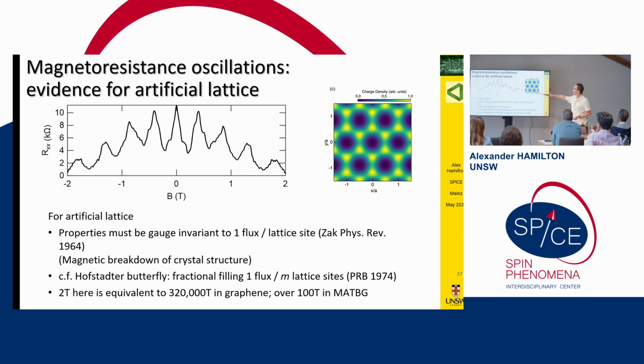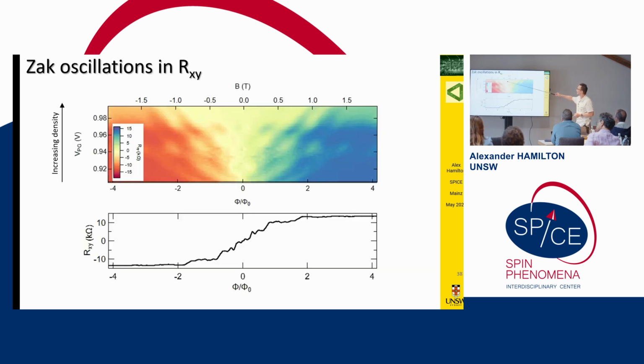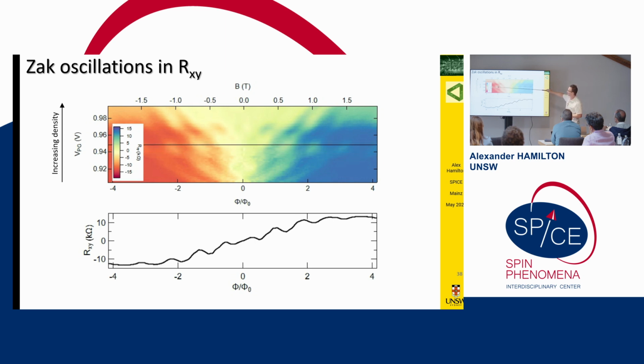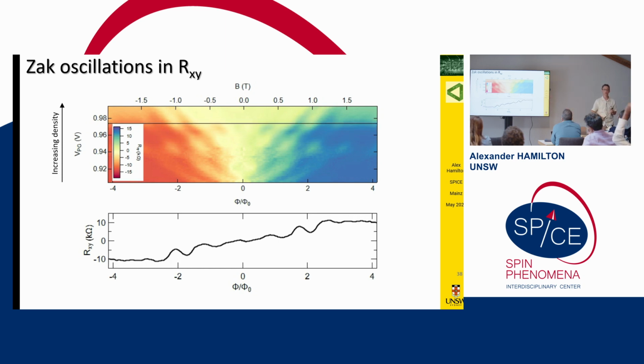So for us, going from 0 magnetic field to 2 Tesla is equivalent to going to 320,000 Tesla in graphene, or over 100 Tesla in magic angle graphene. We're threading so many flux quanta through this lattice that we're completely breaking down the original crystal structure. And if you look at the Hall voltage as a function of flux per unit cell, this is the Hall voltage plotted here, and then you just increase the chemical potential, so just by sweeping the gate voltage, you can see these periodic oscillations here. You can see these kind of stripes here, and the system just shows these periodic oscillations as I gradually thread more and more flux per unit cell.